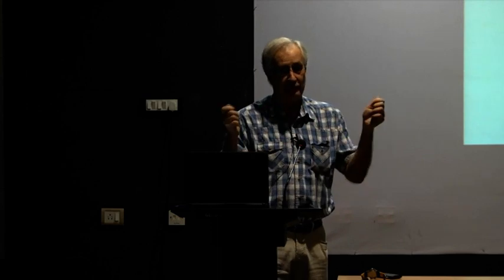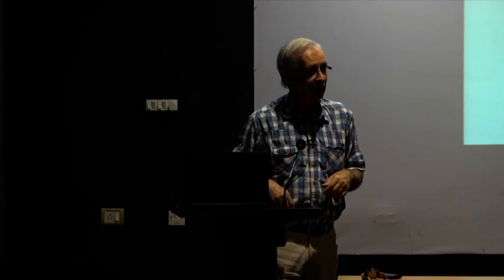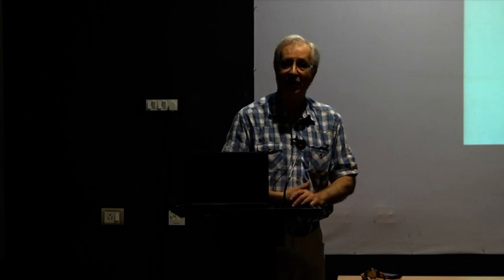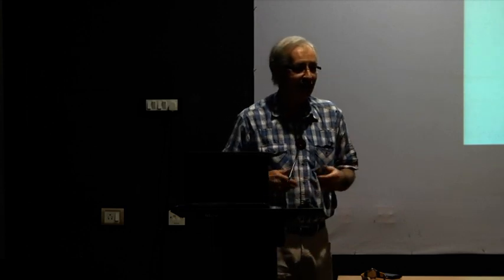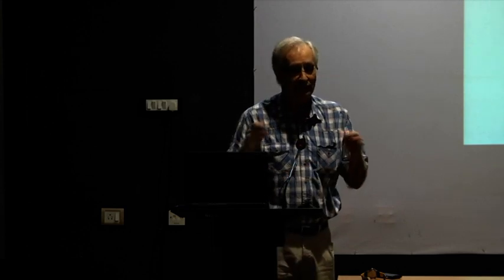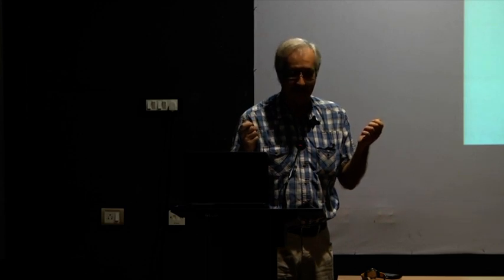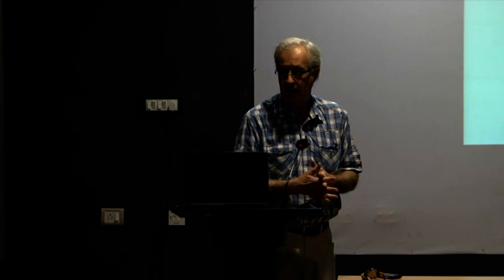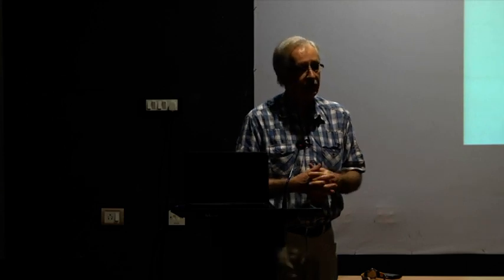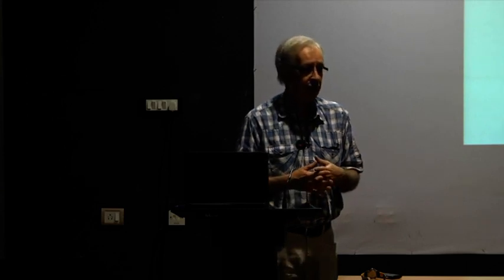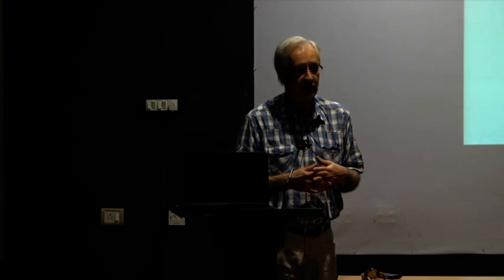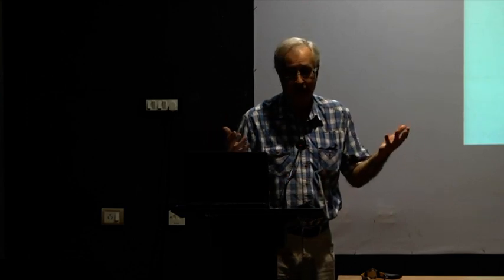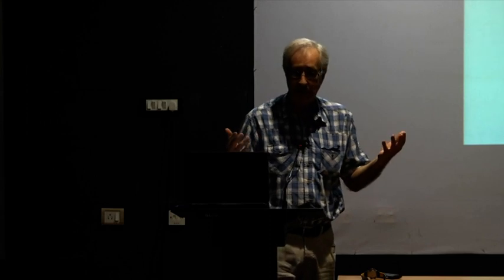Now, this is very nice. You can bend this back and forth, but it turns out that there are other problems. There are fatigue problems, and at some point, it breaks. But people have gotten around that problem by adding some third elements like copper. Then you have reversibilities that are practically unlimited.